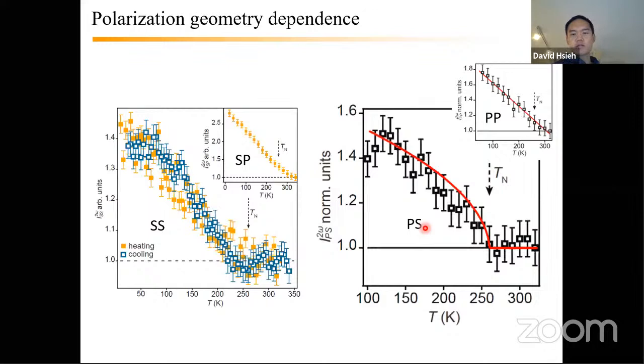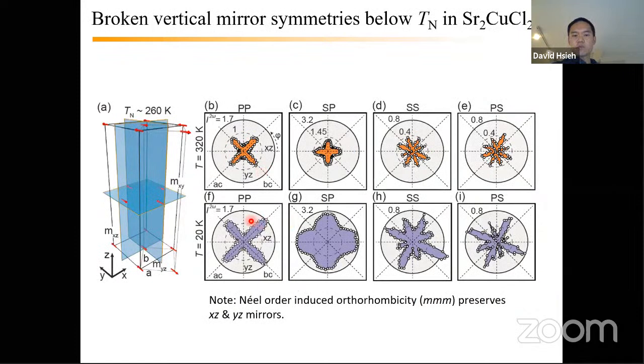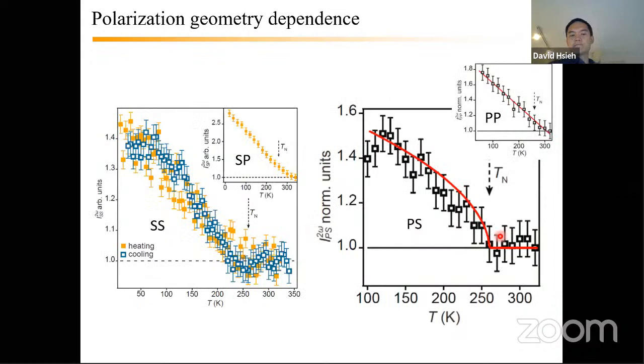What's also peculiar is that if you look at the S output channel, SS or PS, then I do see a feature at T_N, roughly, where the SHG turns on, maybe in an order parameter like fashion. And there's no thermal hysteresis that we were able to resolve, consistent with some continuous transition. But in the P output channels, SP and PP, we don't see any features at T_N. That's consistent with the fact that we don't see any clear symmetry breaking in the PP or SP channels, just in the SS and PS channels. There's a little bit of a slope on these SP and PP temperature dependencies that we now think comes from just thermal contraction effects. We have a paper on the arXiv explaining that.